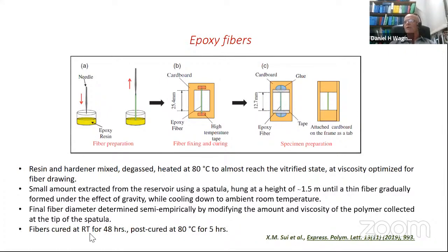The fibers are cured at room temperature for 48 hours and then post-cured at 80 degrees for 5 hours. So this is a technical thing. It's critical in this case, because if you don't follow very carefully something like this, you are unable to make epoxy fibers.